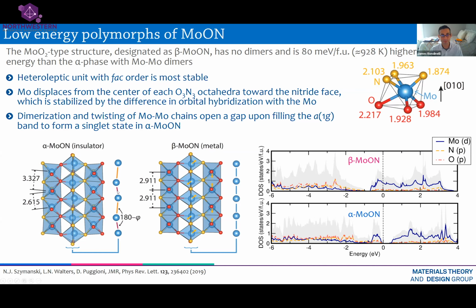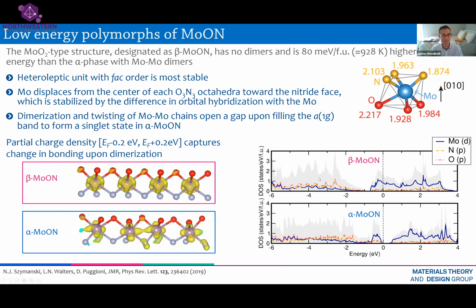When this dimerization happens, shown in this chain direction on the left, the electronic structure reconstructs, a gap opens, and the Fermi level is found at the top of the valence band, and we have a filled state. This is the singlet state, which we saw occurred also in vanadium dioxide. So molybdenum oxynitride is a candidate metal insulator transition compound, which mimics what we saw in vanadium dioxide.